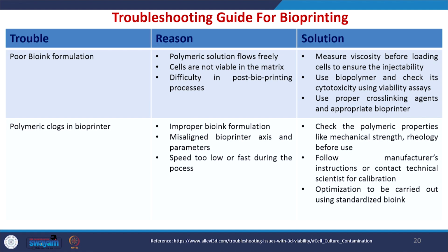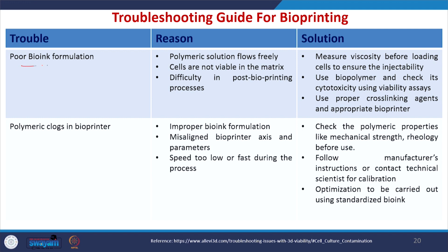Let us learn about the challenges we face when we do 3D bioprinting and how to overcome those challenges. The first problem is poor bioink formulation. The reason may be that the polymeric solution flows freely. That can be overcome by measuring the viscosity before loading the cells to ensure injectability.